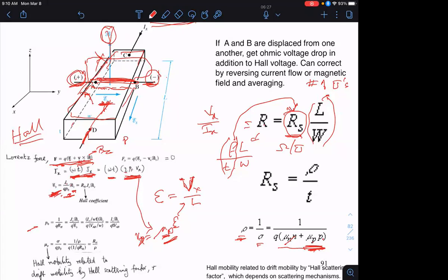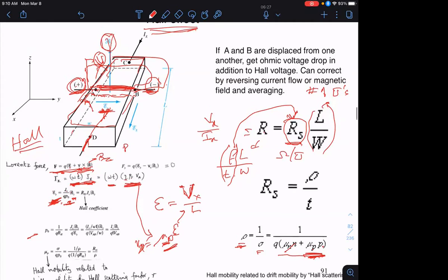Now, to measure the Hall field, all that I need to do is apply a voltmeter in the Y direction, and I measure the Hall voltage divided by the width of the resistor, which gives you the Hall field E_y, okay? Once again, this measurement of Hall effect and the resistance is something you'll be doing constantly if you do research in the field, because you're always interested in, if you make a device, what is my hole carrier concentration and what is my carrier mobility? And these two measurements give you a simple way of measuring those, all right?